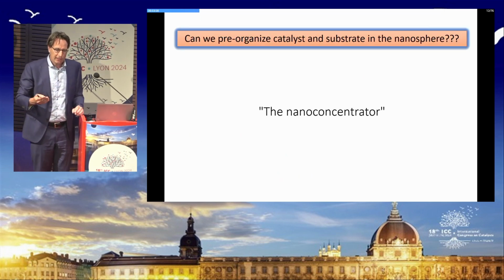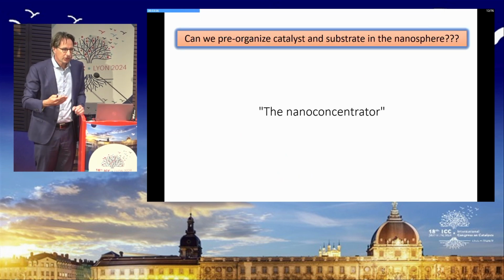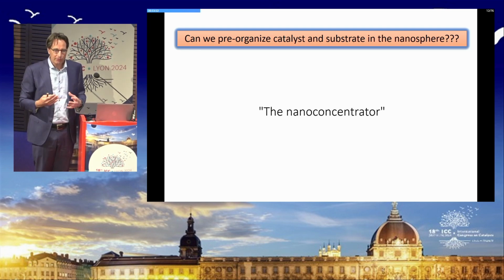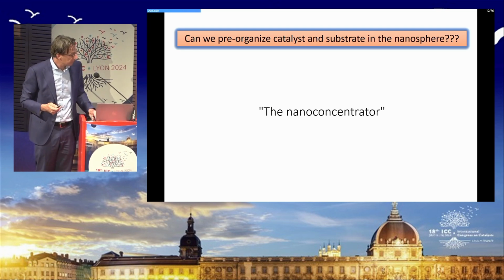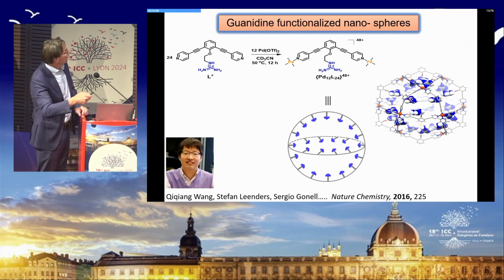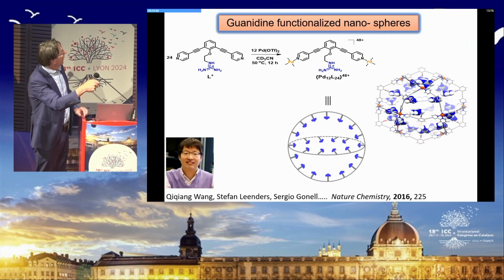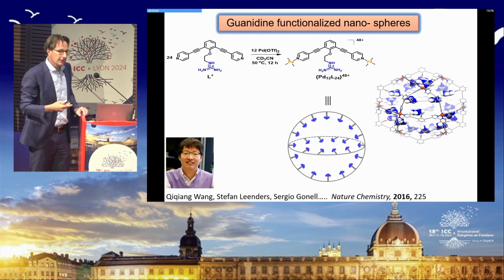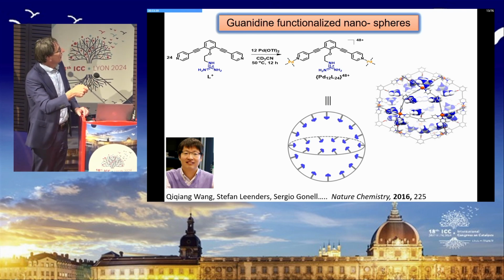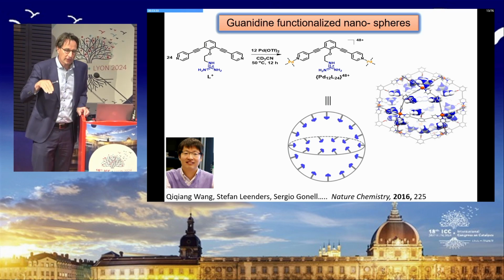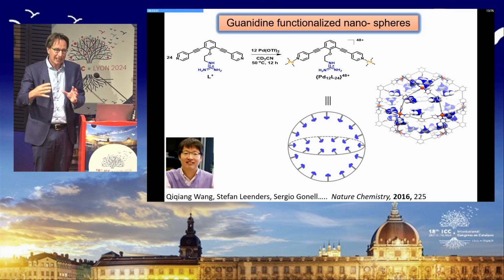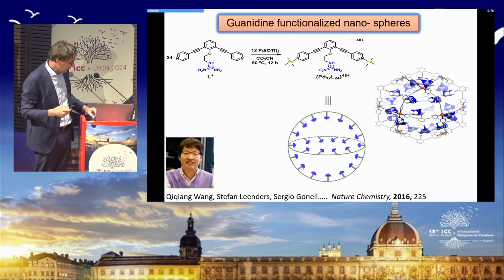So next we thought, okay, it's quite tedious to make new cages each time you want to change the catalyst. Can we also do this in a supramolecular fashion? So Qiqiang Wang, he's now in Beijing, he developed this ditopic building block with a guanidinium hydrogen bonding site. And if you add palladium or platinum, you get these cages, nano cages, with 24 of these guanidinium hydrogen bonding sites